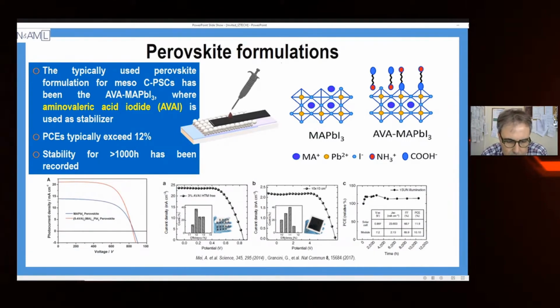Perovskite has a strong interaction with moisture, with the humidity of the environment. That's why it is a real problem. In that case, with this additive, we can improve the interface between carbon and perovskite. This is a really stable technology, because the perovskite is protected in this structure. It is not exposed directly to the atmosphere. And finally, we can get over 1,000 hours of stability, of course under dark. The efficiency recorded for this kind of technology is around 12 or 13%, which is pretty good for this technology, I would say, made in this specific way.